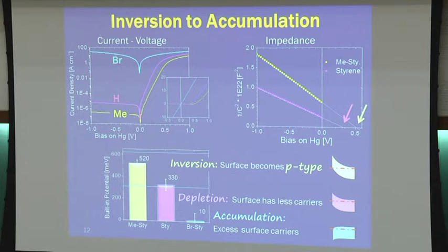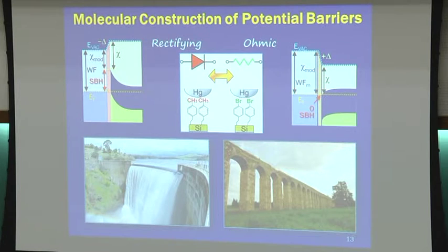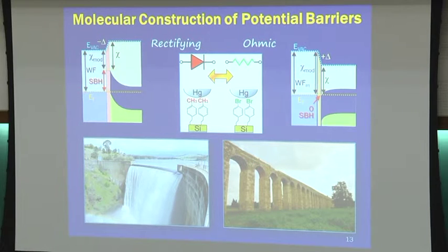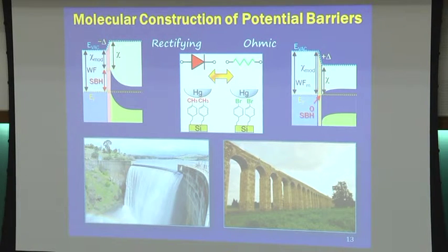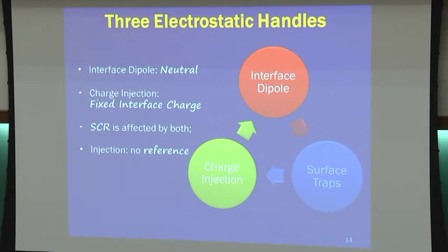And I showed in the talk yesterday that it can be technologically important for solar cells, creating a p-n junction just by induction and not by changing any high-temperature dopant. So that's a summary. With the methyl, we can have something like a very strong gradient. With the bromine, we have something like a conduit. And again, this is just to show that this modification of the molecules has, I think, engineering capabilities.